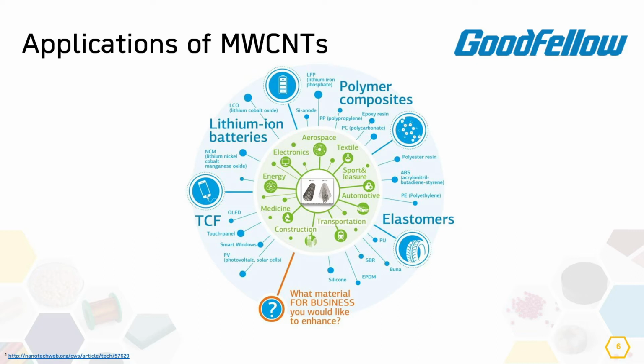displays. Another example of carbon nanotubes is that they are generating fine peaks in optical absorption and emission. So, and that's the importance now for the forest that I have already discussed. So, aligned multi-wall carbon nanotubes emit polarized light by electrical current heating. So, we will have higher brightness emission at a lower voltage compared, for example, to tungsten filaments that have already been used. So we can understand that the properties of multi-wall carbon nanotubes give a great range of application.